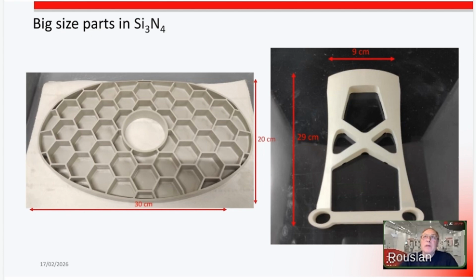Now about the shrinkage, about dimensional deviations, we are using slurries, and your question gives me the opportunity to speak about it a little bit in detail. This technology gives the possibility to use highly loaded slurries. It means that we have a big volume of powder versus organics in our slurries, and the bigger this volume, the less the shrinkage. Usually our shrinkage for different materials, and I don't want to lie now because I don't have the right figures, but I think for alumina we are at a level of between 17 and 19% shrinkage. And for silicon nitride, maybe over 20%, between 20 and 23%.